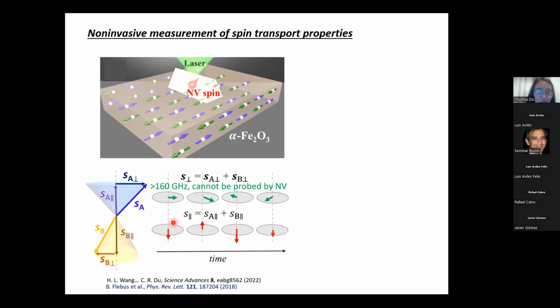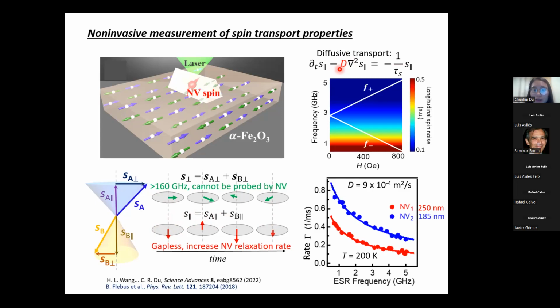However, the longitudinal spin fluctuation is actually gapless. So those low frequency excitations can match the NV electron spin resonance frequency and increase the NV spin relaxation rate. So if we measure the NV spin relaxation rate induced by this longitudinal spin fluctuation, we can probe the spin diffusion constant. According to the theoretical model from our collaborators, Yaroslav Tserkovnyak and Benedetta Flebus, the longitudinal spin noise shows very strong frequency dependence. It is strong at low frequency, then decreases with increasing frequency.